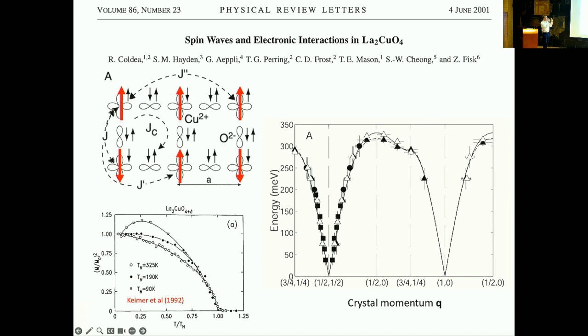So these are quantized spin flips, which move through the lattice with defined momentum and quasi-particle energy, and we can map the energy of those magnon quasi-particles as a function of their wave vector within the Brillouin zone. And this is the kind of dispersion relation you obtain, and from that you can actually extract the strength of these exchange interactions between the different sites in the material. So that's a pretty standard